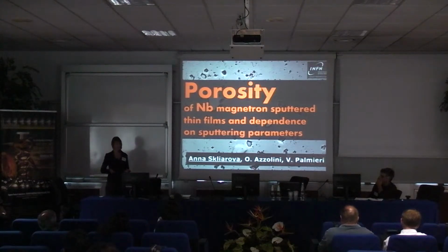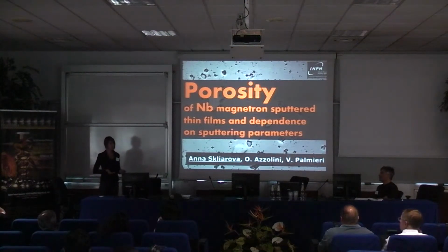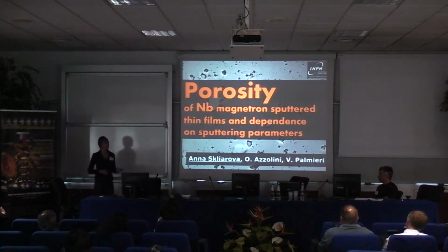Also, surface defects can cause pinholes, like some protrusions can cause shadowing during deposition and afterwards leave a hole, or some pitting after chemical treatment of the substrate can also be repeated in a coating.